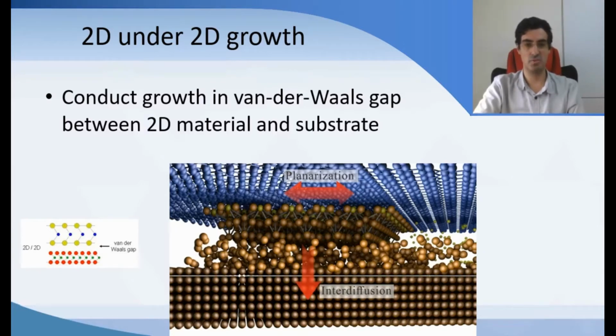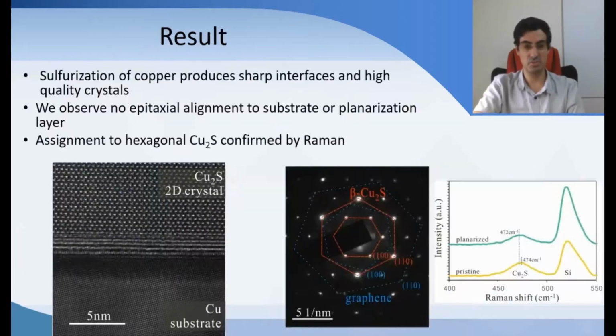And so we can get chalcogen atoms in there, and then we're expecting that the reaction would happen either in a lateral direction or by the chalcogens reacting with the substrate. The substrate in our case is a metal, so chalcogen compounds could just form that way. But we find that the presence of a 2D material actually makes the planar reaction, or the diffusion sideways, much more efficient than the interdiffusion into the substrate.